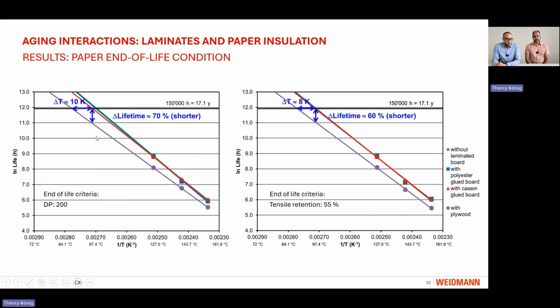And we can see here that the lifetime of the paper is shorter when it was aged together with laminated wood. When you take an end-of-life criterion of a tensile retention of 55%, we can also plot in here the points when this was measured, extrapolate this curve down to lower temperature, and see that the lifetime of this paper is reduced by up to 60% when it is aged together with laminated wood.